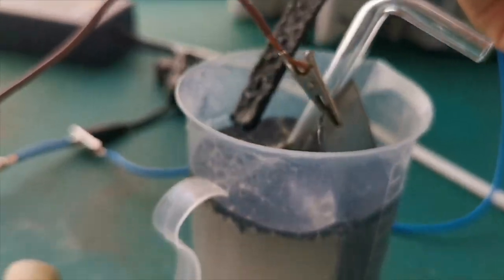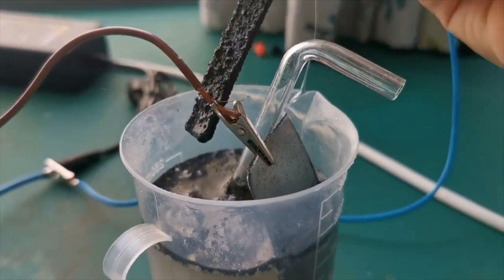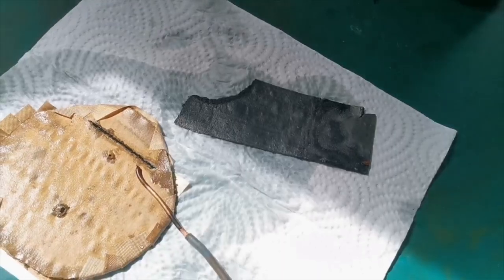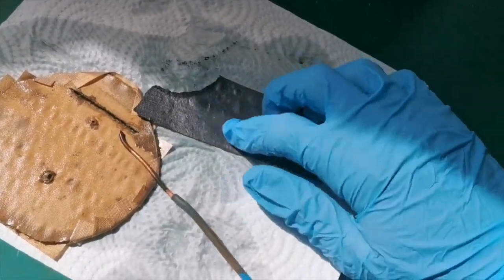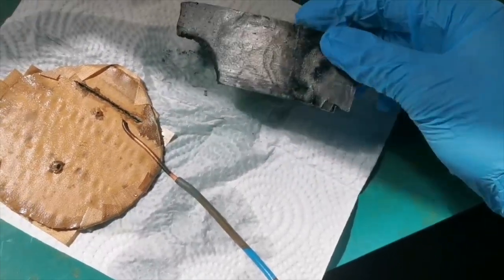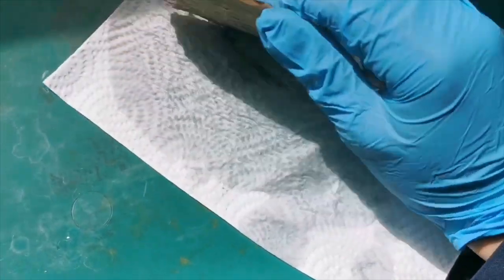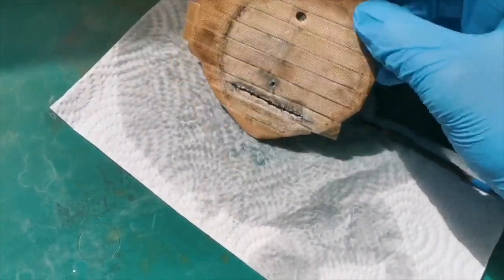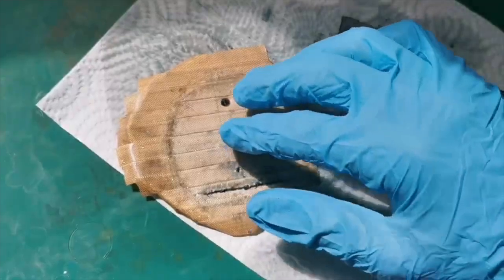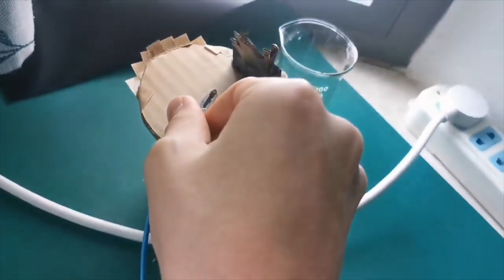However, I realized after some time that the graphite cathode was having a ridiculous amount of corrosion, and released a lot of graphite particles in the solution. I swapped it out for a copper wire cathode, and I decided to modify the cell a bit. The cells before had the problems of corrosion, salt creep, and high resistance. I added a cardboard cap with PTFE tape on one side to the cell, and punched some holes in it for the electrodes. I also used the alligator clips in a different way. It was no longer a part of the circuit. It just helps holding the copper wire directly to contact with the electrodes. In this way, we can minimize the resistance on the contact points.